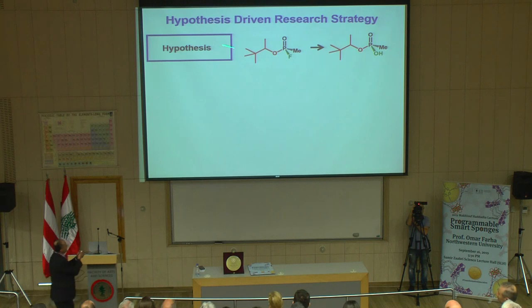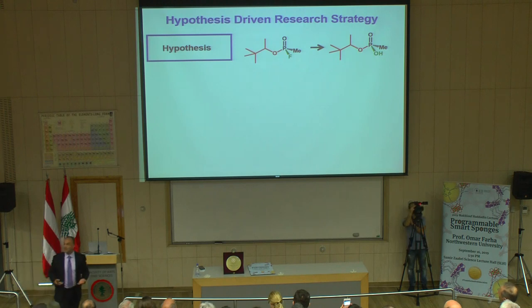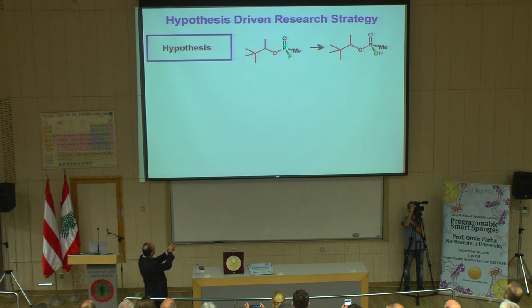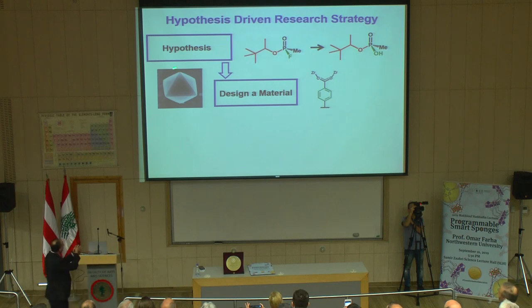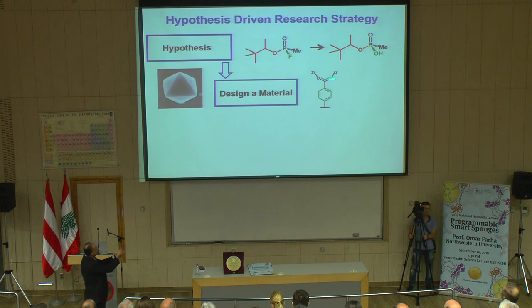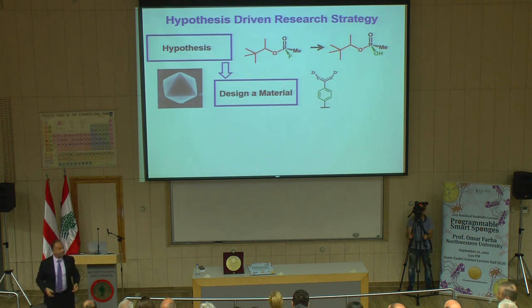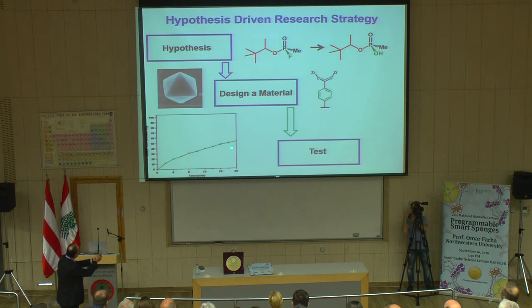So in our lab, we would like to do what we call hypothesis-driven research, and not just shake and bake and mix and see what you get. So what do I mean by that? Let's say the hypothesis is that you want to run this reaction and hydrolyze this P-F bond into this P-OH bond. Because we grow this material and we know the crystal structure, you know exactly what material you want to make. In this case, as an example, we found that zirconium is a good Lewis acid catalyst. So we made the material and ran the catalysis. I'm just giving this as a quick example of how we go around the problem. We tested, it was okay.